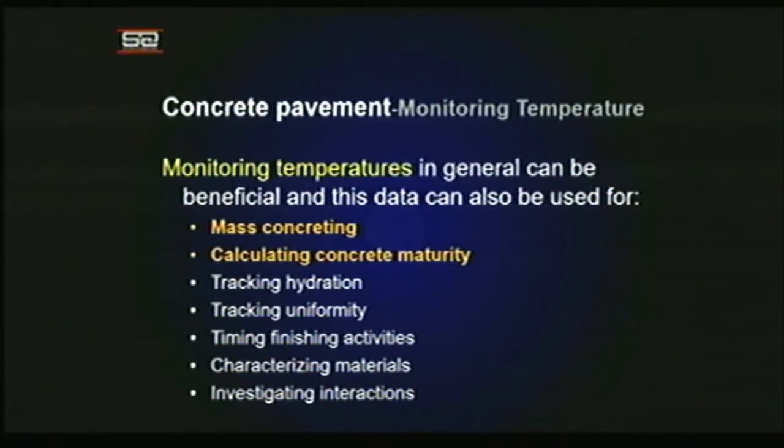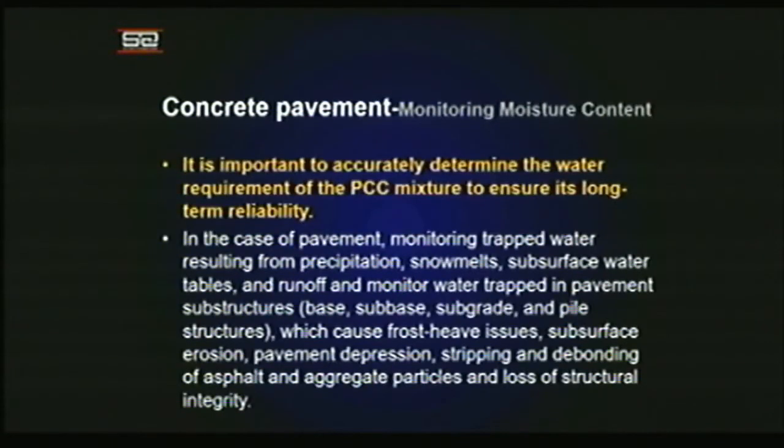And at present, when we are talking about concrete innovations, what is required is calculating the concrete maturity, which has been quite accepted worldwide. It is also based on standard procedures laid out in ASTM, as well as tracking of hydration, tracking uniformity, and timing finishing activities. These are the things that can be monitored using temperature sensors. When you are monitoring temperature, you also need to monitor the moisture content or relative humidity, because most of the curing takes place on the field using moisture, the water.